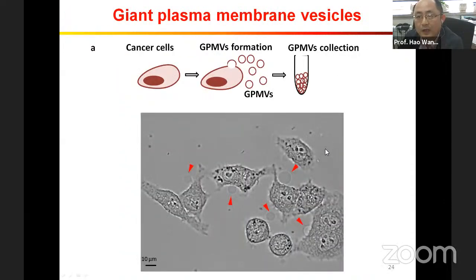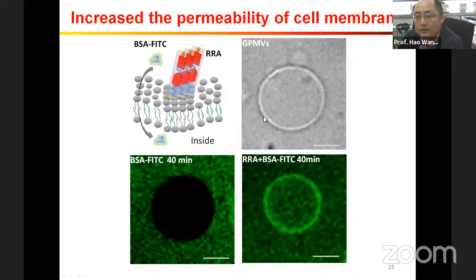We also verified this structure using giant plasma membrane vesicles. We generate these vesicles from the cells, because treating the cells generates this kind of giant vesicle, and we use the vesicle as a model. We treated the vesicle with our material, as well as a fluorescently labeled protein, BSA. If the membrane is intact, without damage, this protein cannot go inside the vesicle. You can see there's no green signal at all. But once we add our material, because the membrane is perturbed, the green signal goes inside the vesicle. That means our material can perturb the cell membrane.